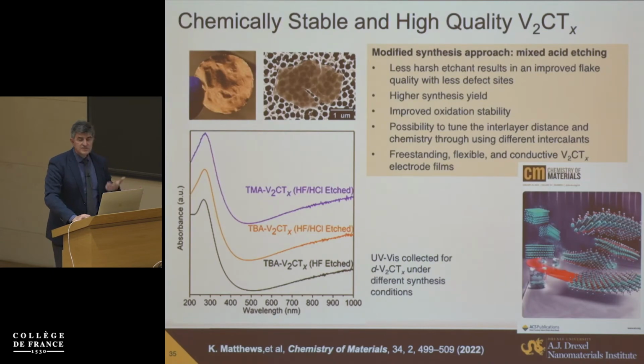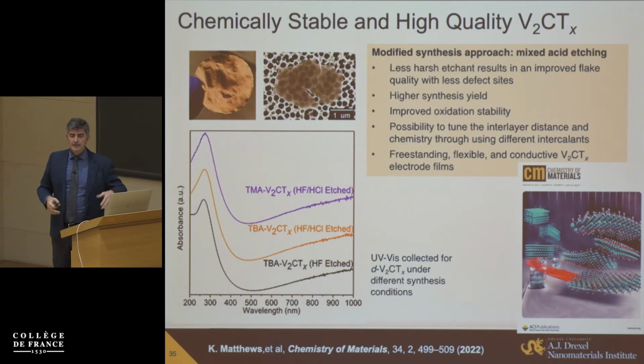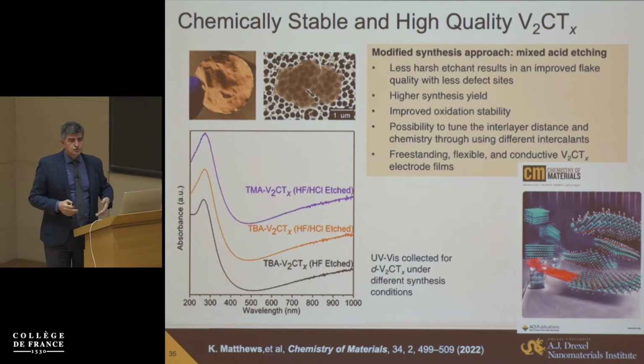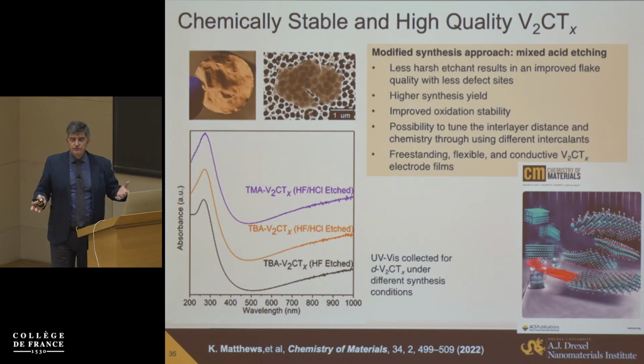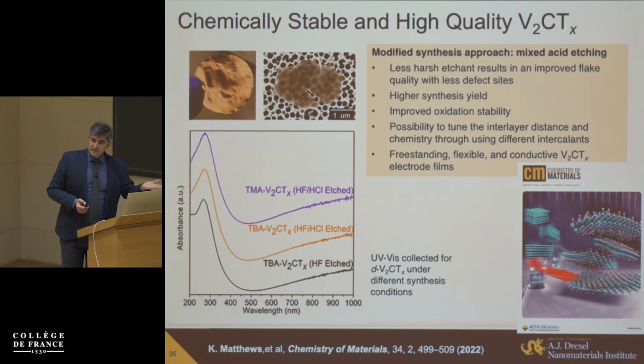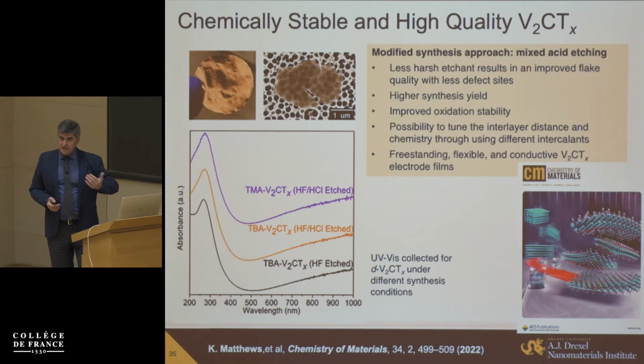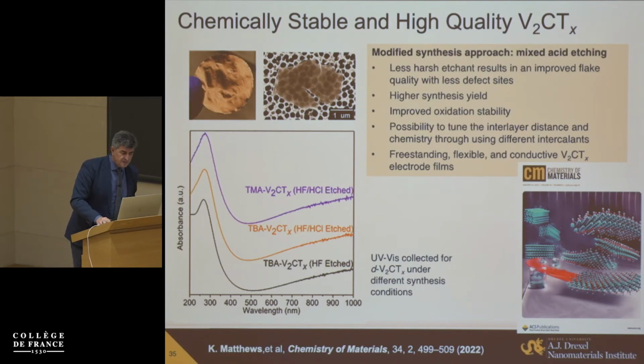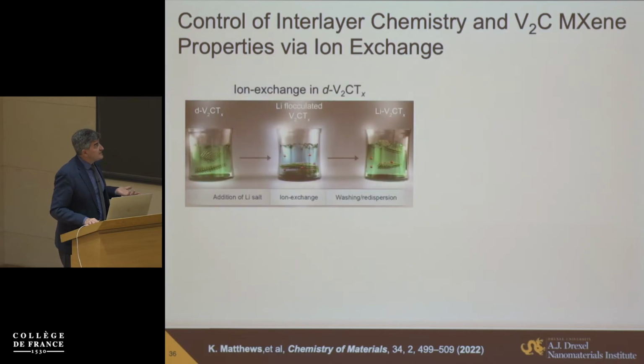And we can play, of course, similar games with many other MXenes, not just titanium carbide Ti3C2. Here is an example with V2C MXene. This MXene was little used before just because it's considered not very stable. In solution, it would degrade within a day, and a film would degrade within a couple of months. But by decreasing the number of defects and changing surface termination, we were able to make it very stable.